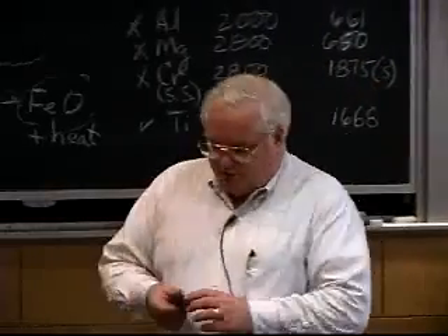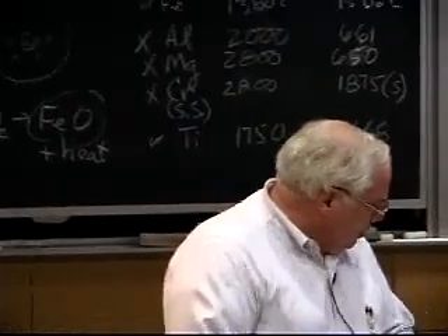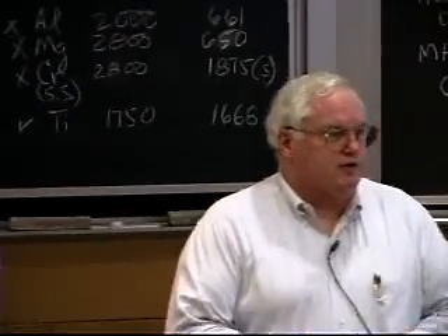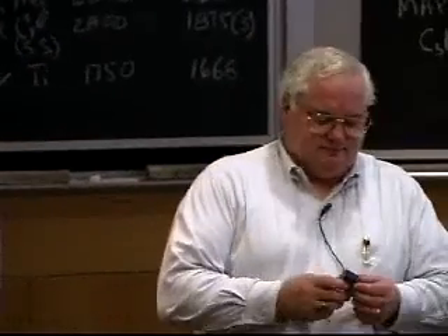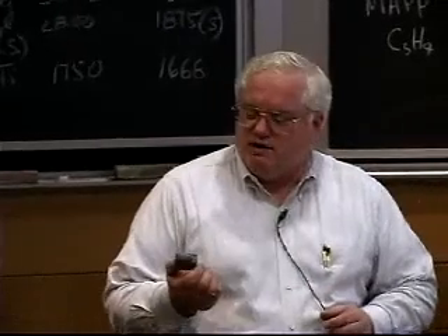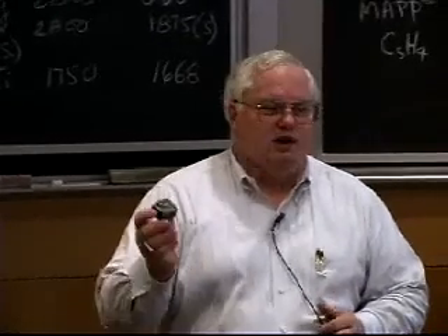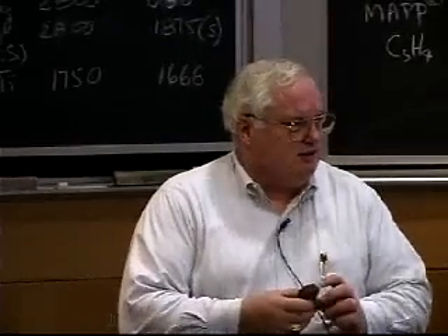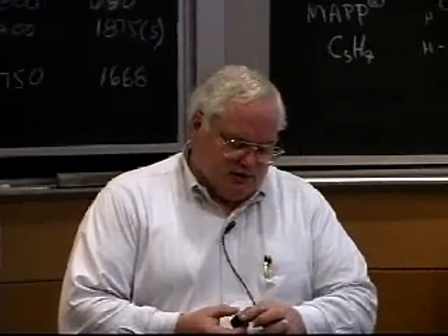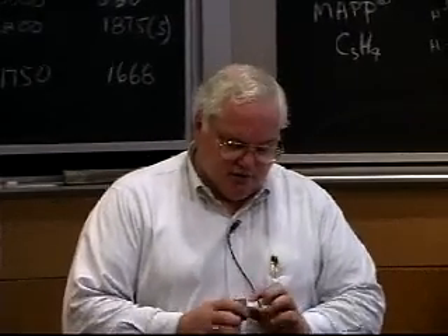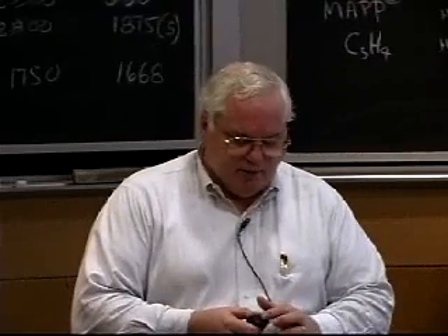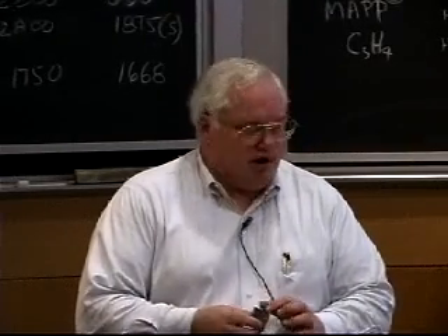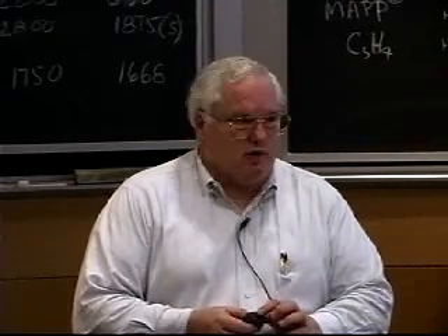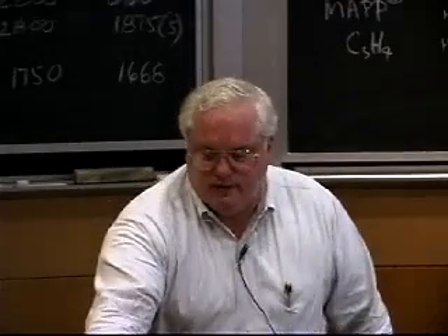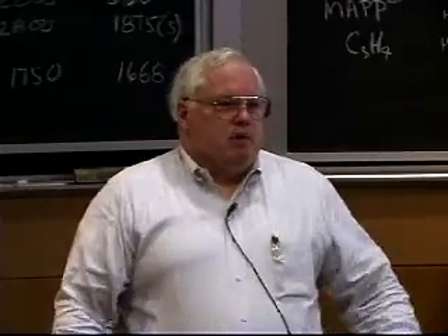If you'd like to see a piece of flame cut titanium, this is the only one I could find in my office. But I don't know, you can look through your office to see if you have one. This actually is, for me, a historic piece. This was my first research contract when I became an assistant professor 25 years ago. But basically, there's a polished edge, there's two saw cut edges, but back here on the back side, you'll see a darker edge, and you'll see the same type of surface roughness. That's a flame cut titanium edge. That's 1-inch thick plate. Flame cut's just fine.